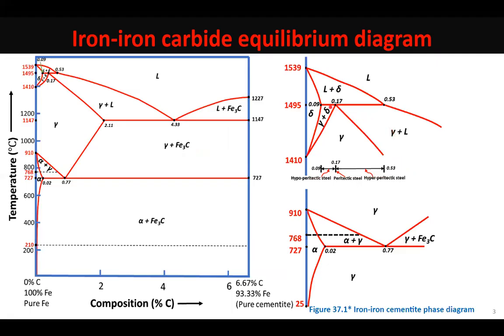So I am now considering that these steels are called hypoperitectic steels. And what do these hypoperitectic steels convey? They contain liquid and delta, but if you look into their microstructure just after the peritectic reaction, just below 1495, you see along with austenite that gets formed by their combination through the peritectic reaction, they also contain delta. What does that reflect? That reflects that this delta was present in excess of that weight ratio 1:4.5.